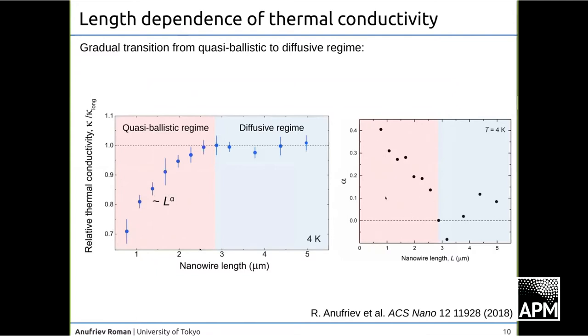And if we analyze this alpha and extract it from these data points, we can see this kind of curve: alpha is the biggest for the shortest wires, and then it becomes weaker and weaker until it gets to zero, or oscillations around zero. It's not real oscillations, of course, it's just experimental error. I mean, it has to be zero. So what we can see is an alpha of around 0.3, 0.4. Very roughly speaking, the heat conduction that we observe is 30% ballistic or quasi-ballistic, with one being perfectly ballistic and zero perfectly diffusive. That is an important conclusion here, and it's at 4K, because in many papers you can see that they measure nanowires and obtain alpha equal to one, perfectly ballistic at room temperature. This is something that is very hard to reproduce with a statistically reliable study, I would say.